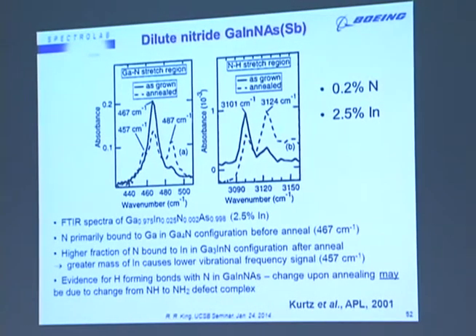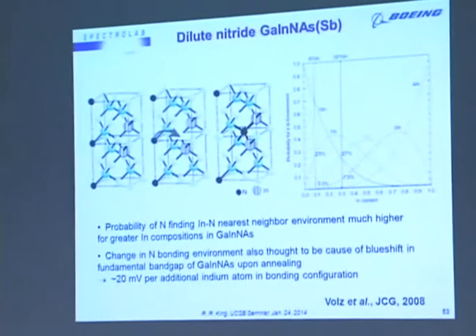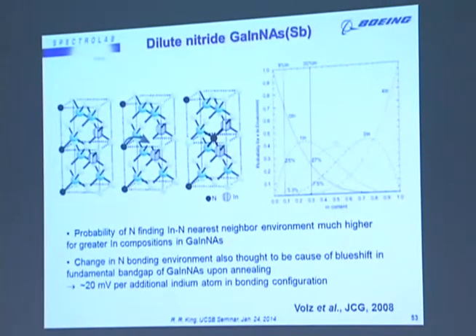The shift of this peak also seems to be correlated to hydrogen forming bonds with nitrogen as we anneal, and that's also thought to be one of the more important defects controlling recombination in the dilute nitrides. So this is just schematically the nitrogen shifting over its position in the lattice to be closer to indium as a nearest neighbor upon annealing.